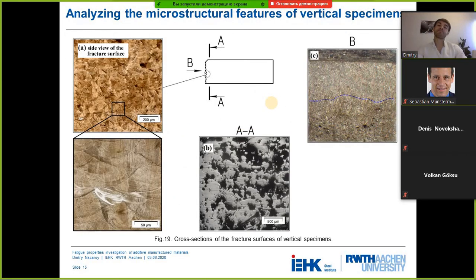In order to explain all of these differences, a decision was taken to investigate the microstructure, do porosity analysis, and fractography analysis. Here the vertical specimen is presented, and on the side view of the fracture surface, the morphology of the specimen is elongated columnar grains. Here we can see that the grains are even elongated beyond the laser tracks.